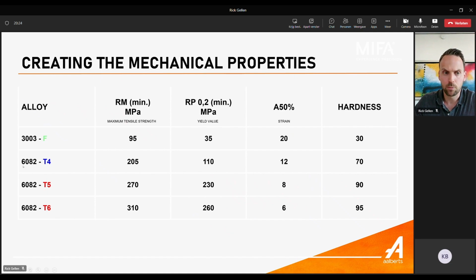For the next example, I took the alloy 6082. If we do hardening by nature, so we do not do the process, but you leave it after the extrusion, then the strength goes from 205 to 110 megapascal. But if we do the hardening process, you harden to T6, you see the strength gets really up to 310 to 260 megapascal, but the strain is getting lower. That's the difference, what the mechanical properties are doing with the heat treatment.